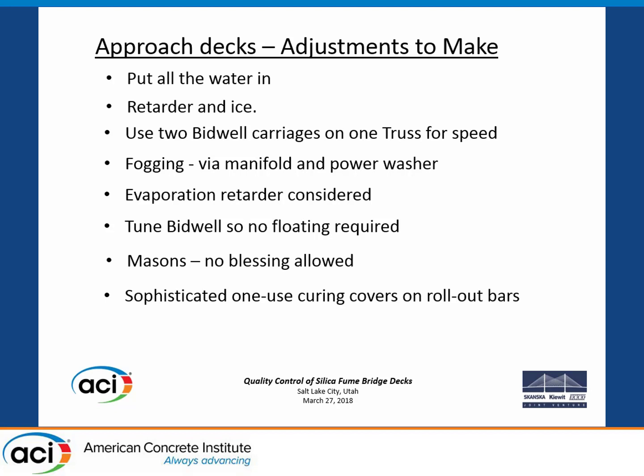So you can wet the diaper on the bottom as it goes out, and then it's got pinholes, so you can put water on the top of it. The pinholes will just suck the water right in and keep them wet. Okay, and wet only is required. You don't flood the deck because you're putting that 55-degree water on an 85-degree deck. You're going to shock it. And that's an ACI policy, too. I think the biggest spread you're allowed is 20 degrees or something like that, but only as required. Just keep the diapers wet.